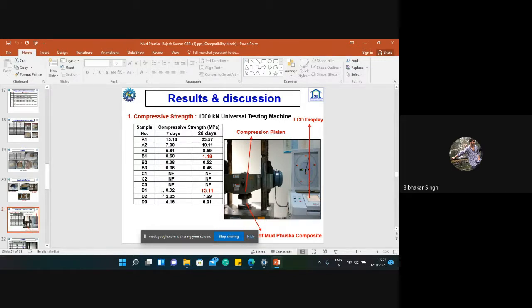We found that the sample made of soil, crumb rubber, cement, and water showed the highest results: 13.11 MPa after 28 days. But we did not choose the highest compressive strength value just because we have to see other properties also, like whether it is lightweight or not, and the thermal conductivity of that mix proportion.